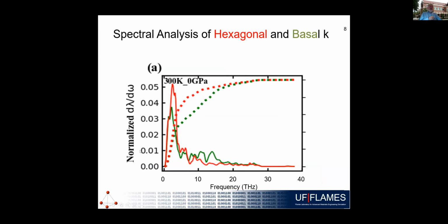And so what we're seeing here is that most of the energy is being transported by these phonons between 1 terahertz and maybe 5 terahertz. So a lot of this region here is the acoustic phonons that we saw in Professor Snyder's presentation. But what we're seeing here, maybe above about 5 terahertz, is the contributions from the optical phonons. And in this case, these optical phonons are providing roughly half of the contribution to the thermal conductivity.